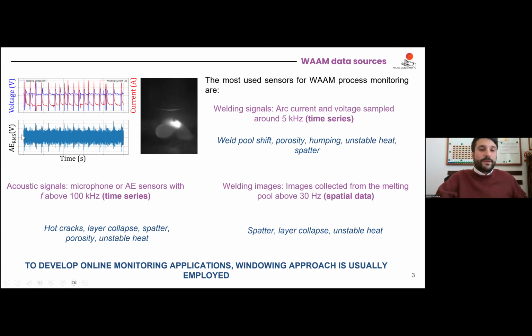Because at the end of the day, as you can see here, there is a correlation between the acoustic emission shape that you are going to collect from the process and the welding signals like the arc current and the arc voltage behavior. So you can see the correlation with the peaks, for example. Another kind of information or data that you can collect is definitely the welding images. So you can place a welding camera on your robot and you can collect at frequency above 30 hertz about what's going on inside the melting pool, and here you can detect again spatter, layer collapse, and as well unstable heat input during the process.